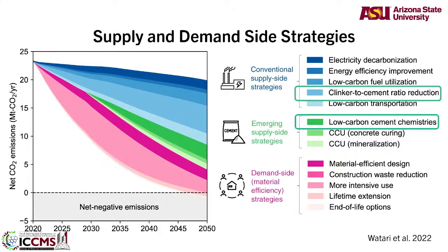But if you look at supply and demand side strategies, these are your conventional supply side strategies. You reduce your clinker to cement ratio. You reduce your clinker content. I don't know, Indian cements are probably at about 0.85, I think. US cements are about 0.82. There are some European cements that have a clinker to cement ratio of 0.7, but the global average still hovers around 0.8-ish.